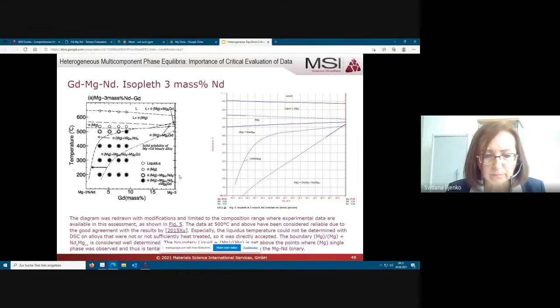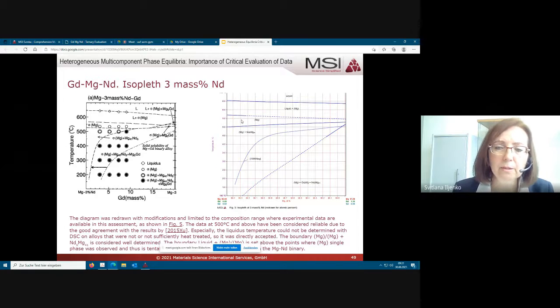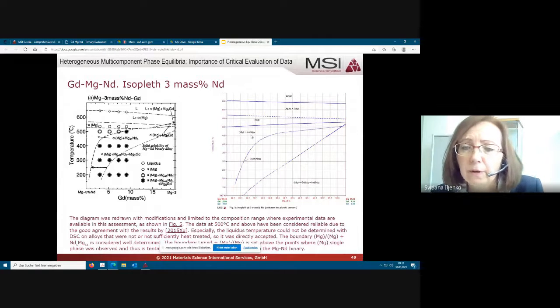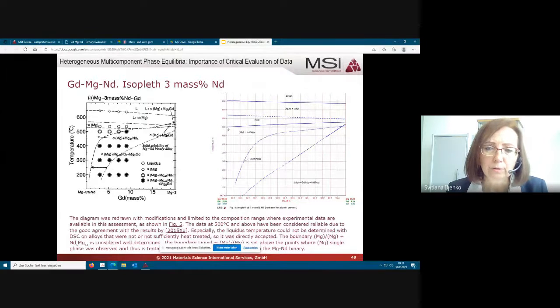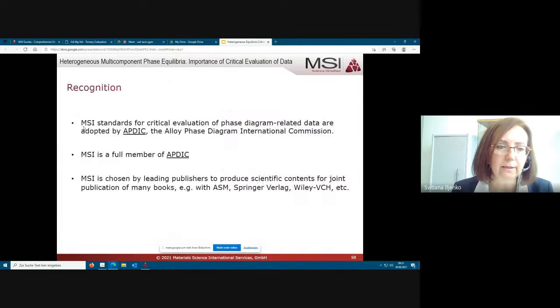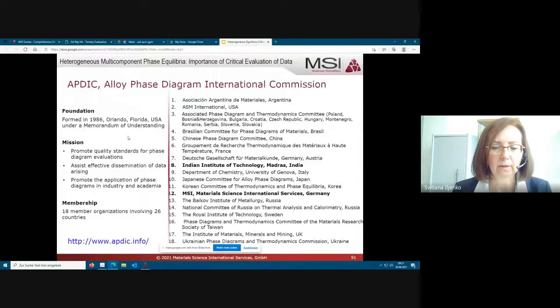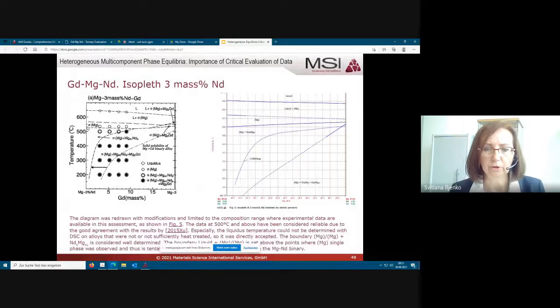And what was not accepted is very well described in the text with the details and showing some points. If you look here, for example, this phase border between magnesium and magnesium plus neodymium 5 magnesium 41, this border also has been modified by our authors slightly. Yeah, if you see, this point is here coming exactly at 500 degrees, and here it is slightly above this temperature. What I wanted to show is that we try to really find what is reliable, what is less reliable, and in some cases what is less reliable can also be presented if our experts consider this as feasible. But in some cases it is just skipped from the presentation.